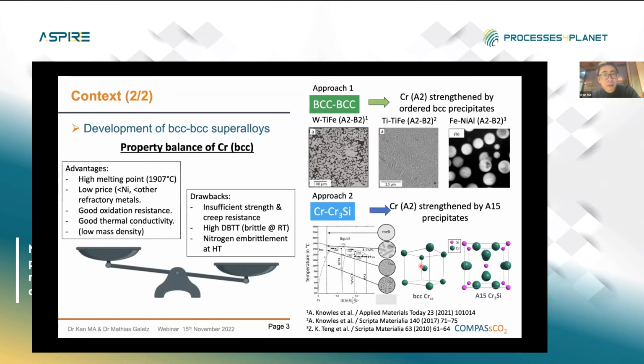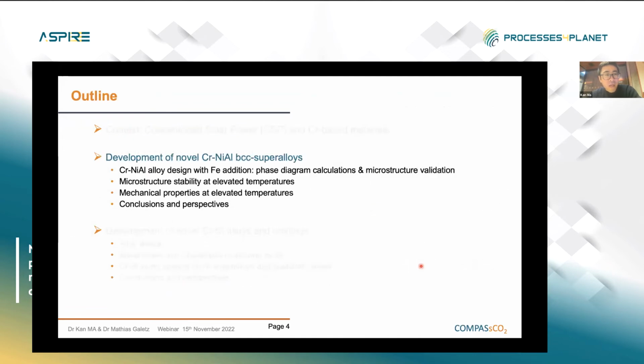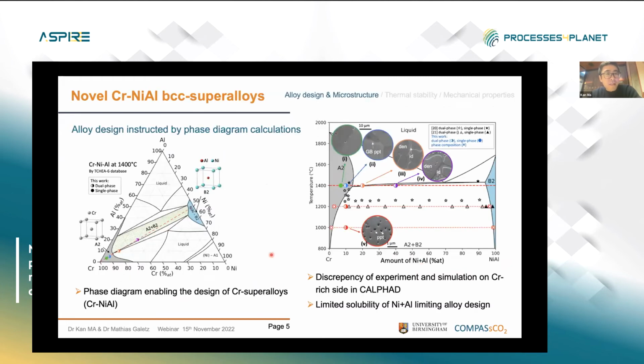nitrogen resistance. So in the following, I will present the first part, the development of novel chromium nickel aluminide BCC superalloy. And in fact, the design of this alloy is instructed by the phase diagram calculation. As you can see in this ternary phase diagram, we have a single phase chromium area and a single phase B2 nickel aluminide ordered BCC phase, and with a dual phase intermediate.